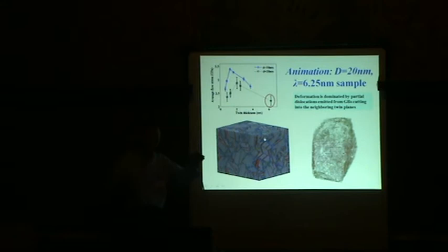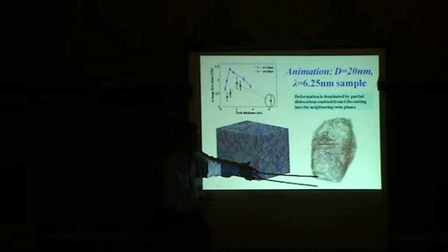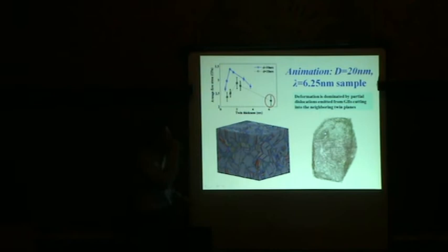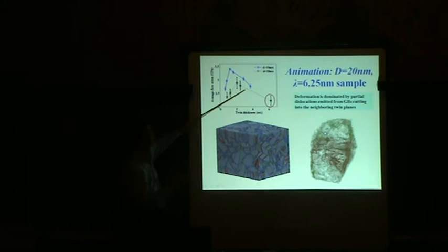go against the barrier, pile up, and then penetrate the barrier. So this picture is very similar to the classical Hall-Petch picture, where defects pile up against the wall. And if you watch, this is the top one grain. Taking one going out, we also see this kind of forest of dislocations, just like the G.I. Taylor simulation, dislocations coming from all directions and from the forest. So in this regime, we're in a classical Hall-Petch regime, where dislocations pile up against twin boundaries and penetrate. Okay? So as the twin boundary spacing decreases, the stress goes up.